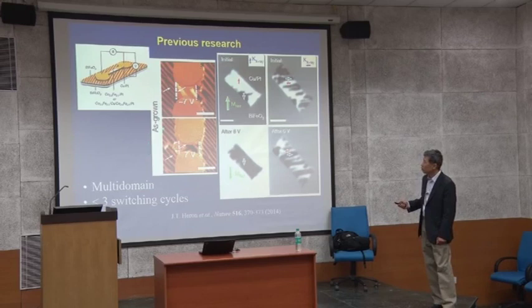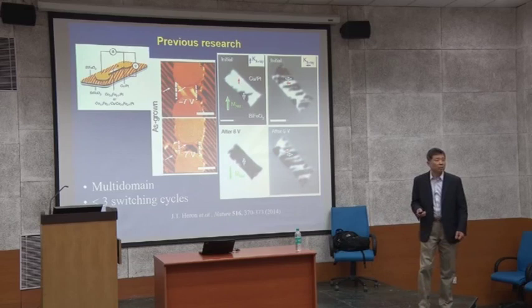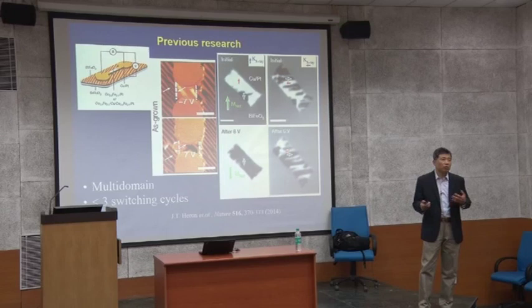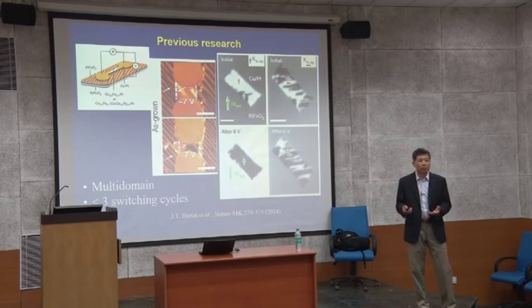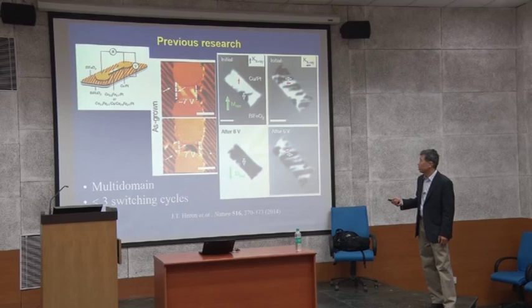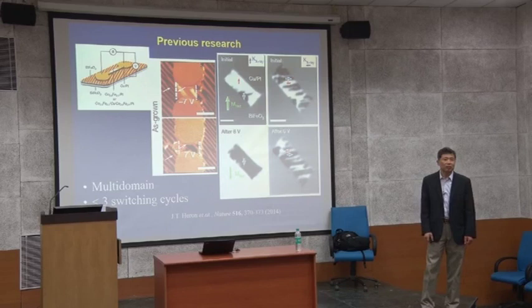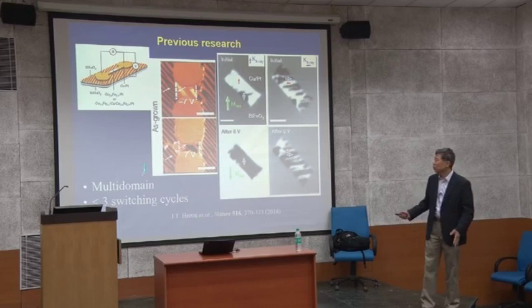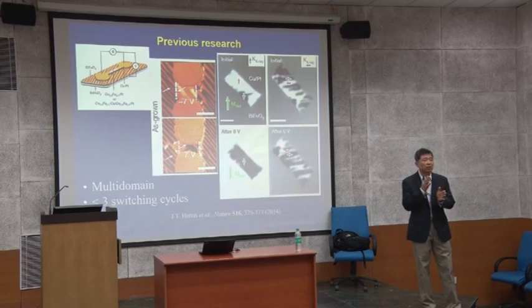When you try to look at exactly what mechanism is happening, it is very difficult to determine, because you have an average over the complexity of this material. So this is one way; we make this, and it works, and that's fine. But there are two problems. Due to the multi-domain structure, the interpretation is very complicated. The other problem is that you have a lot of domain boundaries, and we do not know whether the phenomenon is coming from the actual domain or from domain walls. A domain wall is another grain-boundary-like behavior, and it plays a lot of interesting roles.